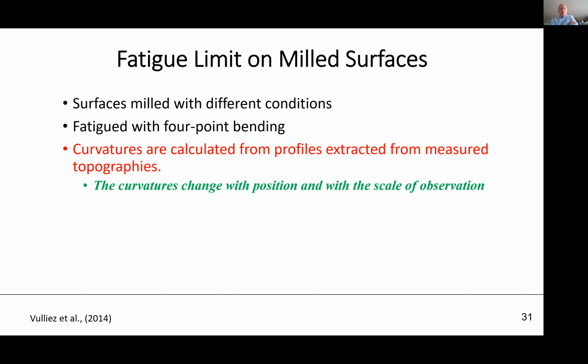This is one of my favorites. It was also done with a team at ENS Cachan in France, at the same school. Here we're looking at the fatigue limit on milled surfaces. So we have surfaces that were milled with different conditions, fatigued in 4-point bending. This was all done in France, and this was somebody's doctoral work, just doing this part. Then Vulliez came here and worked with us one summer, and we calculated curvatures based on an algorithm that was developed by our undergraduate students.